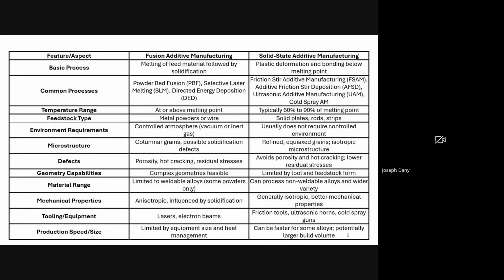With respect to defects, fusion is more prone to porosity, hot cracking, and residual stresses, whereas solid state processes avoid porosity and hot cracking and also have inherently lower residual stresses. Coming to geometric capabilities, fusion is very attractive because it allows us to build highly complex shapes and geometries, but solid state methods are somewhat limited because the tool must physically access the build area and the feedstock form can restrict the geometry.